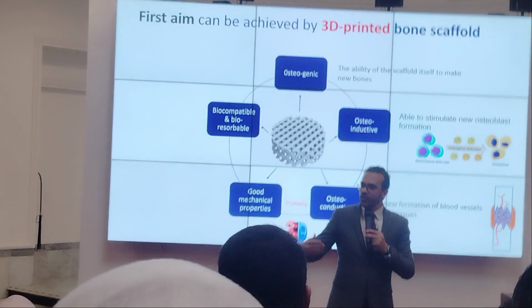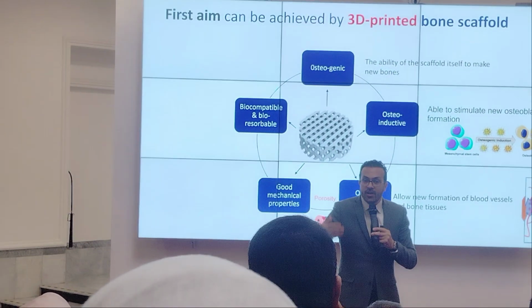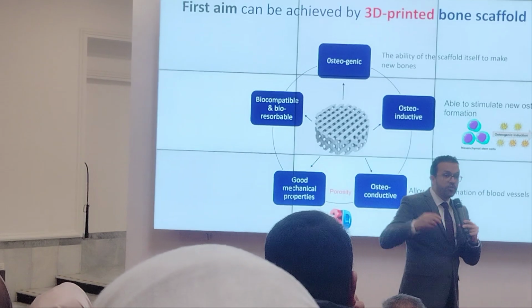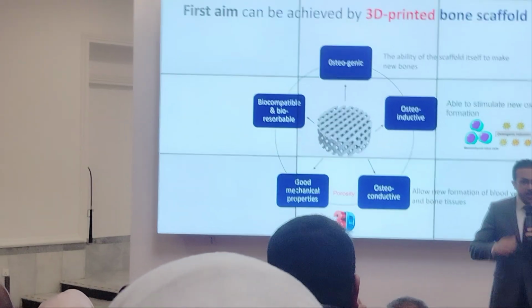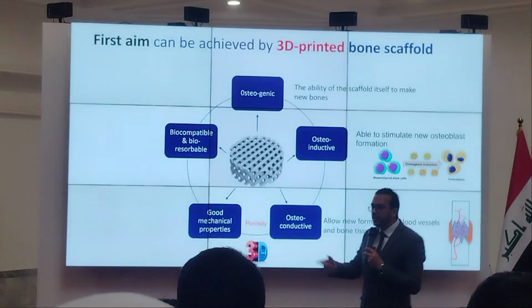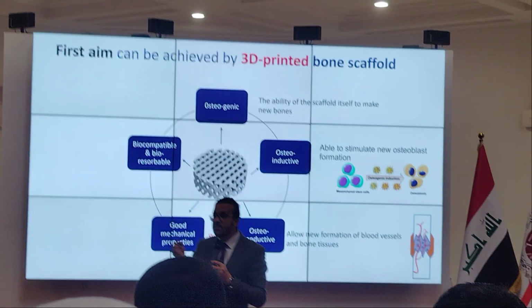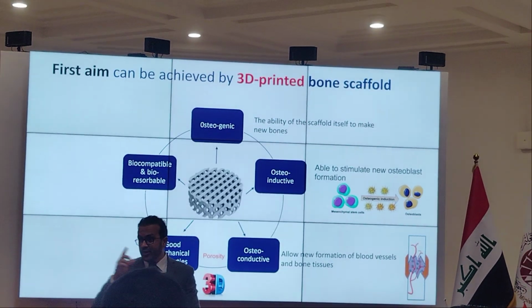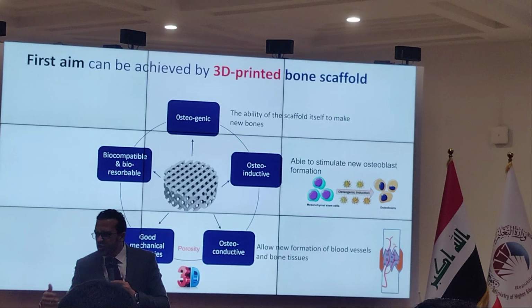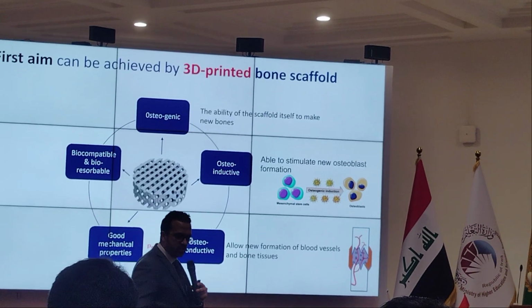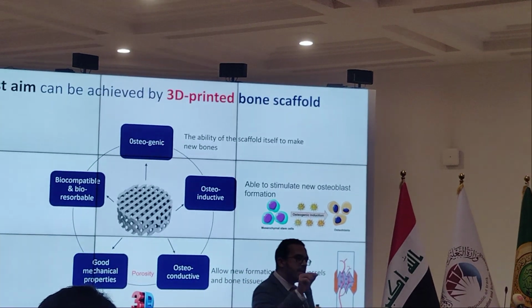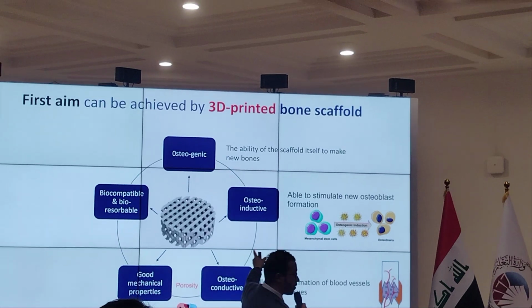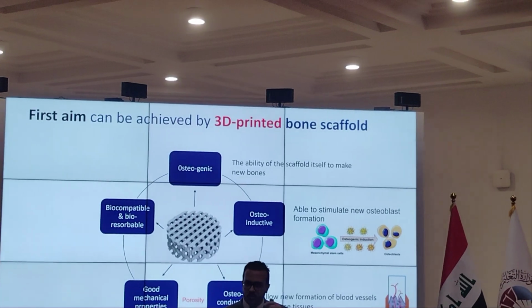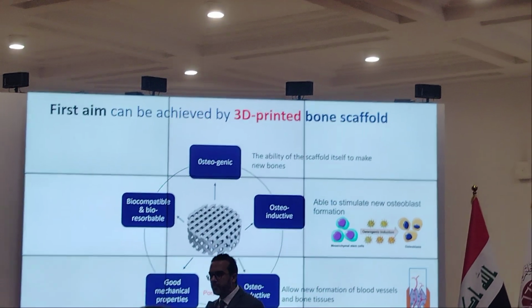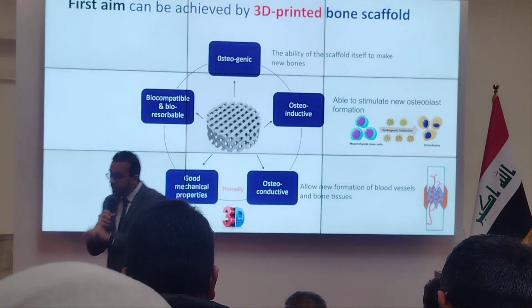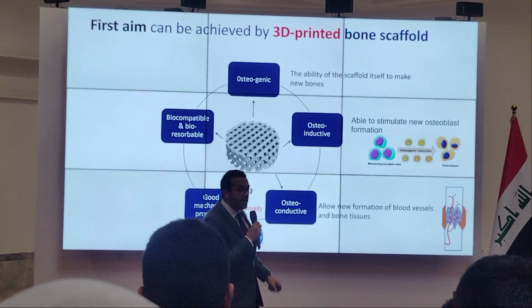So there's a good chance of recovering the main shape of bone, especially if we're talking again about kids. And moreover, this scaffold, due to its porosity, can be loaded with stem cells. So this also can be used for adults. If you don't have a chance for bone growth, no problem. We will incorporate stem cells loaded inside these pores, of course surrounded with an optimum biochemical environment to support the growth of stem cells, and this is called osteogenic.